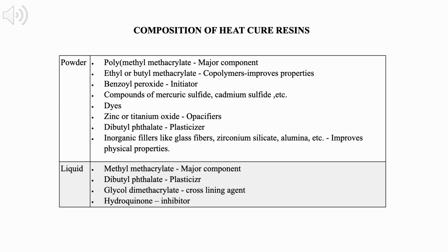Powder. Poly methyl methacrylate, major component. Ethyl or butyl methacrylate, copolymers improves properties. Benzoyl peroxide, initiator. Compounds of mercuric sulfide, cadmium sulfide, etc., dyes. Zinc or titanium oxide, opacifiers. Dibutyl phthalate, plasticizer. Inorganic fillers like glass fibers, zirconium silicate, alumina, etc.